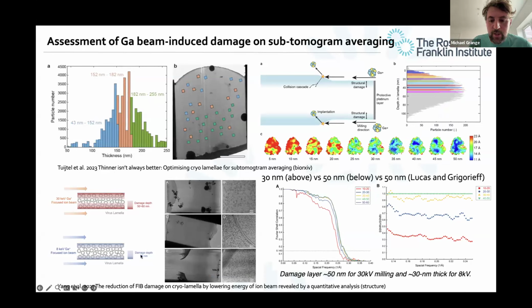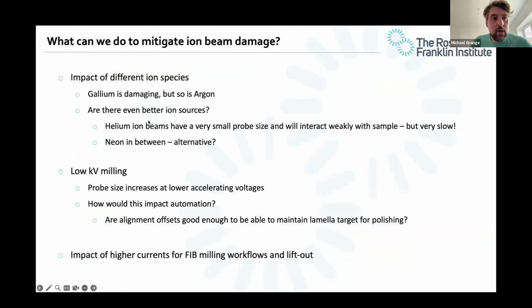There's a recent paper by a Chinese group which showed damage of up to 15 nanometers for 30 kV. And I think what's really important to show with this study is that when you reduce the acceleration voltage that you use for the ion beams, you essentially reduce the damage layer. So there's a lot of potential for low voltage ion beam milling, but it's important to point out that as you go to lower accelerating voltages, your probe becomes much larger. And if your probe is larger and your full width at maximum extends, then you're going to have a greater problem getting flat lamella and milling consistently. So there would be work to do in generating that automation.